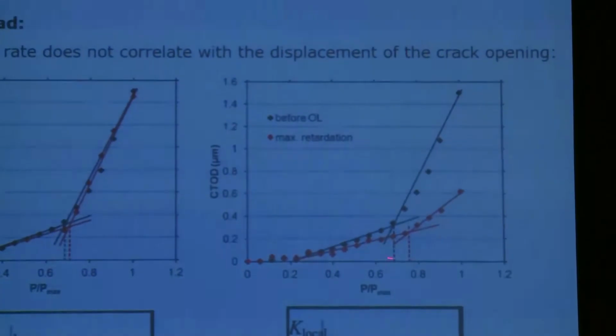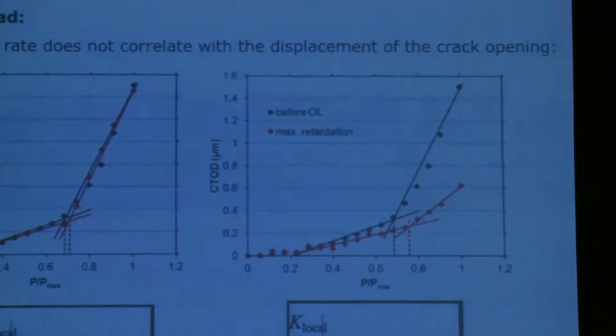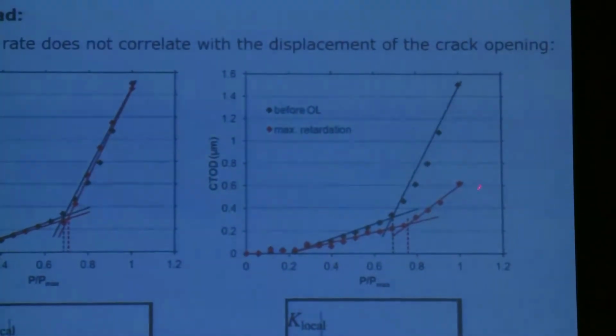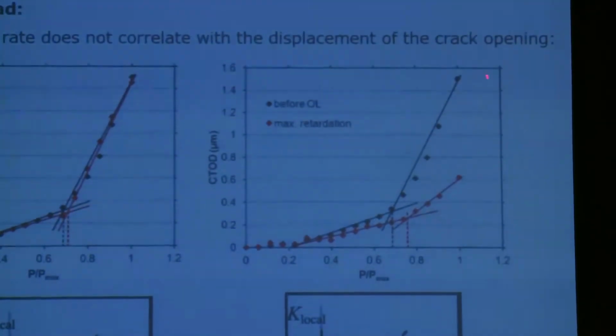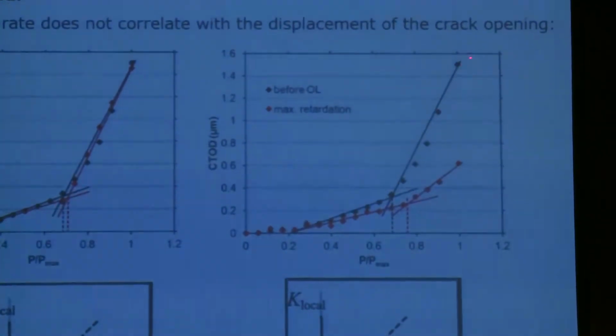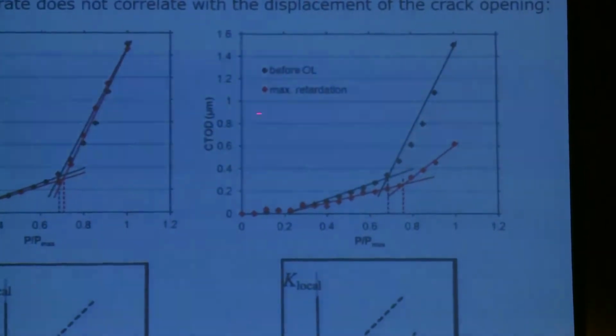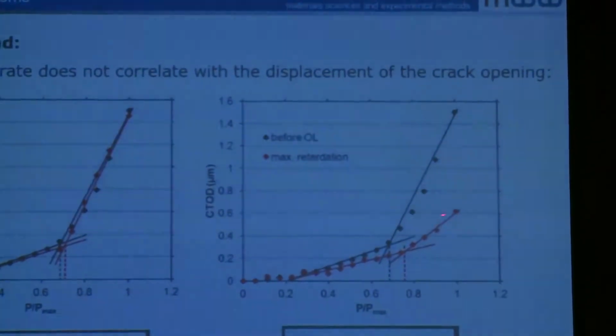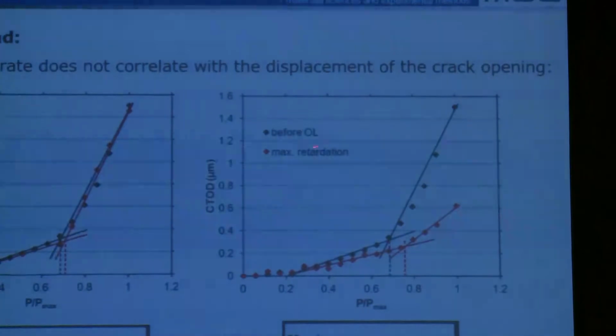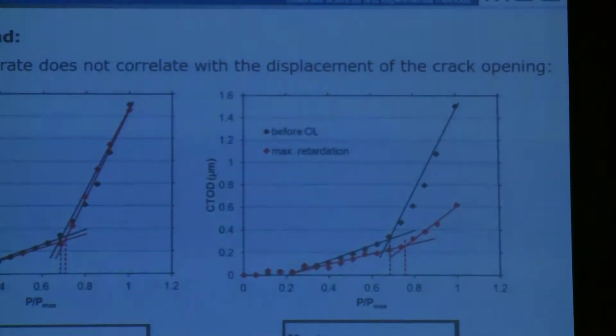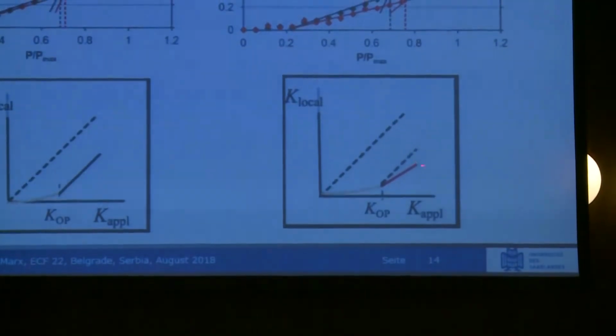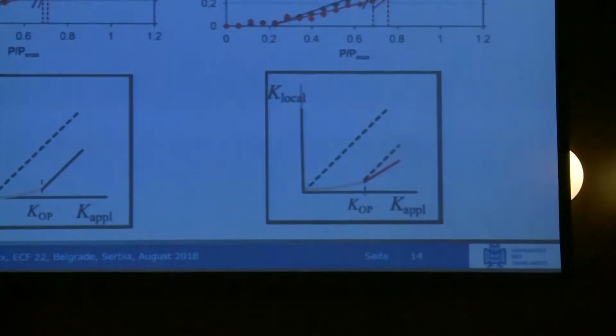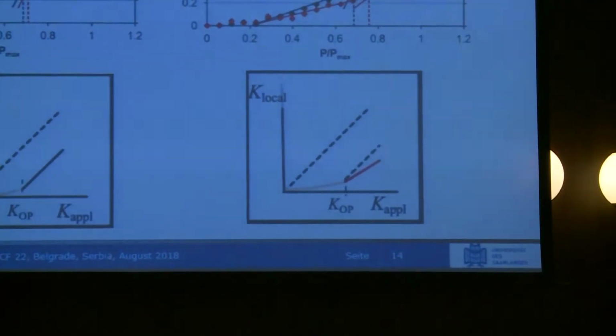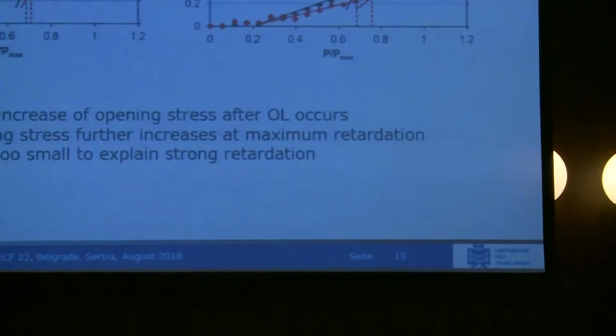Then you see you have only a slight increase of the opening K, but you have a huge difference between the maximum opening in this case before the overload and the crack tip opening after the overload at the position of the maximum retardation, which corresponds to this diagram. This means that here we have residual stresses, because the maximum load is not applied at the crack tip due to the residual compressive stresses.